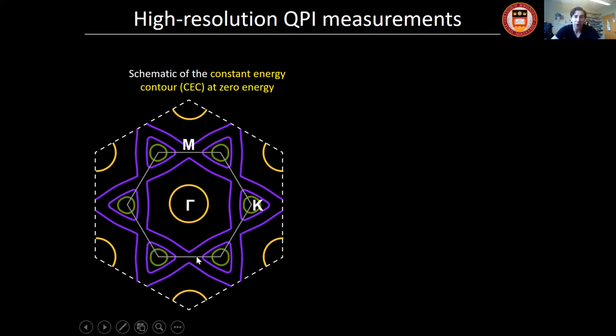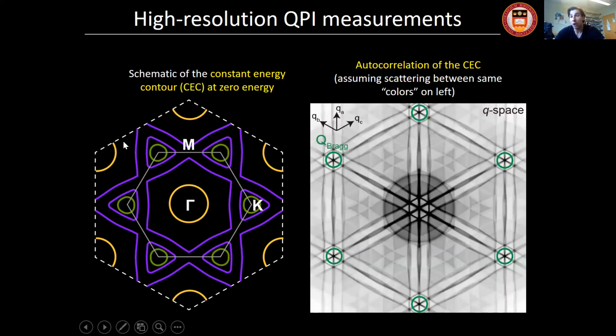But now I'm showing you this constant energy contour at zero energy. This is the Fermi surface, a simplified diagram of it. Different colors represent different bands. This circle at the gamma point is the band that we imaged in our QPI measurements before, but there's a bunch of other bands. So we wanted to see, can you actually see them well? Near the Fermi level, because quasi-particle lifetime is naturally larger, you can maybe be lucky and be able to see other bands as well. So what would one see in STM? Well, we can take this constant energy contour and autocorrelate it. If you autocorrelate the thing on the left, you get this image on the right.